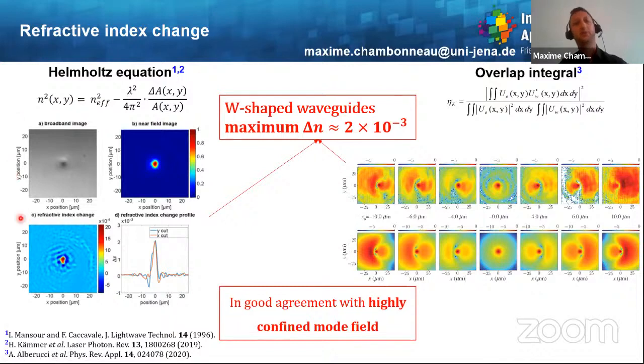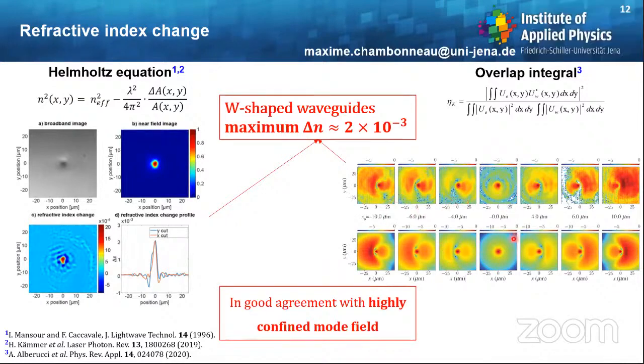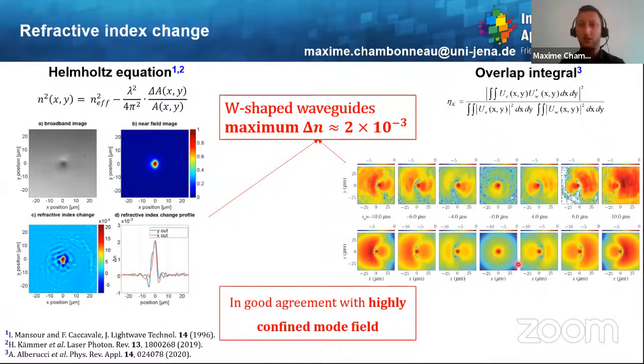So this method I described previously, relying on inverse Helmholtz equation, is pretty classical. When you take a look at the literature, it's known from the 90s. Besides, we have developed, together with my colleague Alessandro Alberucci in reference three, another alternative method relying on the overlap integral coupled to a beam propagation method. With the positioning system we have, which is a piezoelectric stage, we could take some different images when we shift the waveguide with respect to the incoming light and then perform the same simulations, and as you can see, it's working pretty well on this figure.